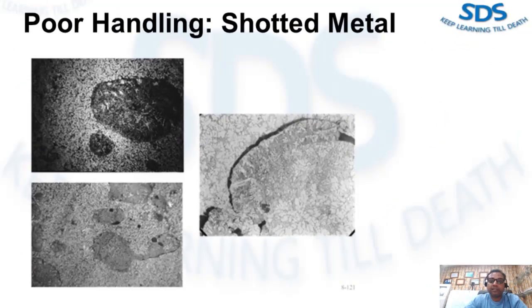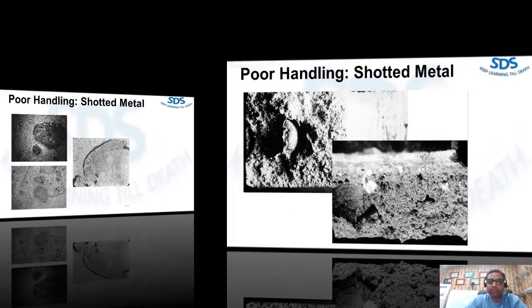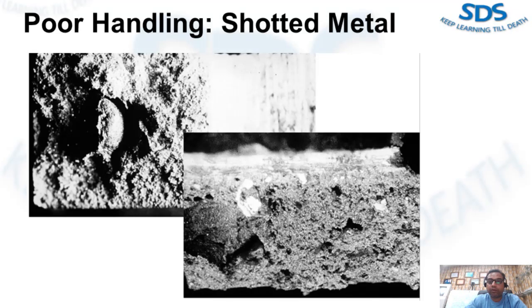These images are further examples of shotted metal — note the oxide film. Shotted metal can also be caused by excessive turbulence in the die caused by inserts or by having several core prints in the metal flow path. One image shows a fractured casting with a ball of shotted metal, and another shows the same fracture with the ball removed. Sometimes a customer will complain of porosity in the casting when it may actually be shotted metal that popped out while being machined, leaving a void that looks like porosity.